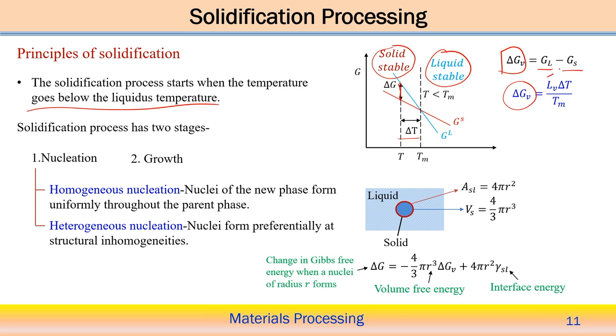The latent heat, delta T by Tm, here we represent the latent heat as LV, with the degree of undercooling and the Tm. So this is the amount of free energy available for the solidification to occur. Now the solidification process is basically two stages, as we already defined: one is nucleation and another is the growth stage. Now there is another division, homogeneous nucleation and heterogeneous nucleation.